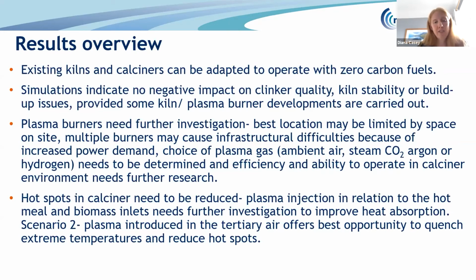So the hotspots in the calciner must be reduced. The location of the plasma injection in relation to the hot raw meal coming in and the biomass inlets needs further investigation to try and improve that heat absorption and make sure the heat's going into the raw meal and not into the side of the calciner. And scenario 2, where the plasma is introduced into the tertiary air, appears from the modelling to offer the best opportunity to quench some of those extreme temperatures and reduce those hotspots.